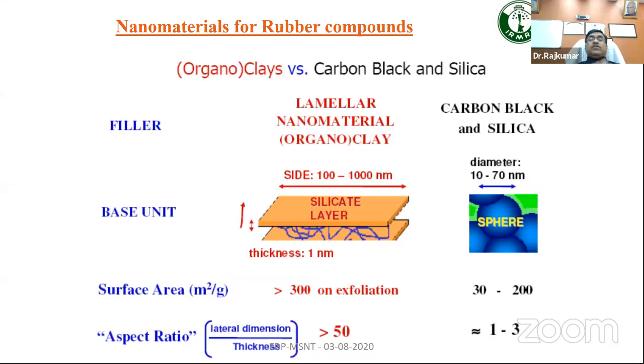When you talk about organoclay versus carbon black and silica, and compare them, the aspect ratio and the particle size differ. Carbon black and silica are smaller in diameter, 10 to 70 nanometers, whereas organoclay is 100 to 1000 nanometers.